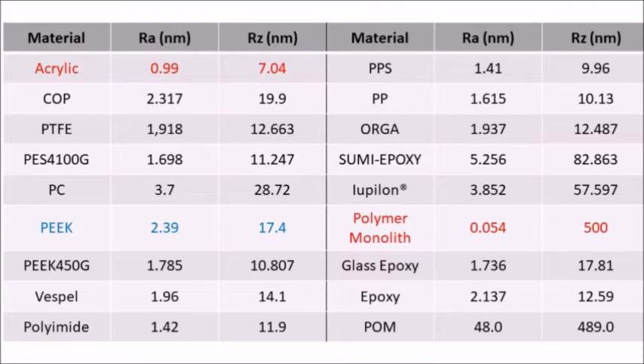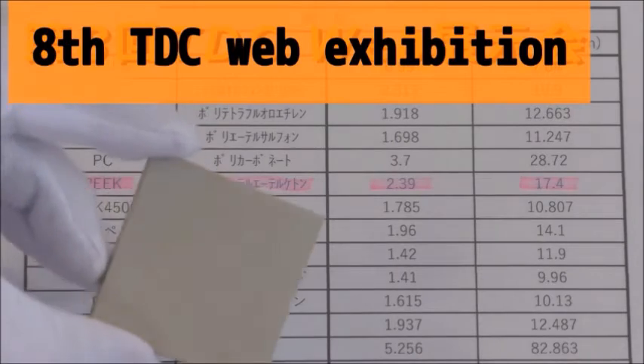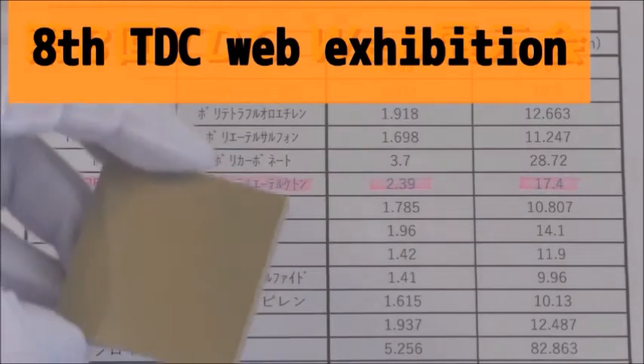The material acrylic has the best roughness. Ra 0.9 nanometers and Rz 7 nanometers. Also, a material called polymer monolith has a great roughness of Ra 0.05 nanometers. I have a sample of the material named PEEK.